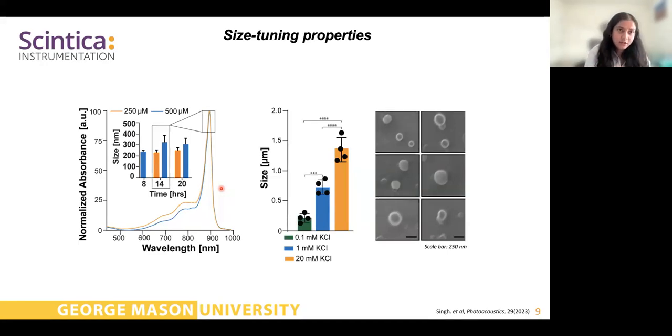And these are anionic dyes, or negatively charged dyes. So we ended up choosing KCl as our first salt for optimization. And we varied the salt concentration along with the total dye concentration and the time of incubation, and incubated all of these solutions at 60 degrees Celsius.